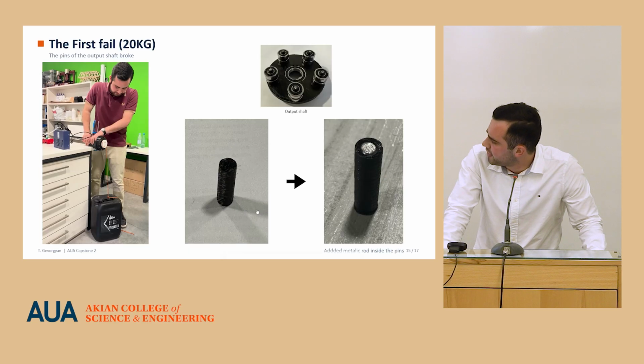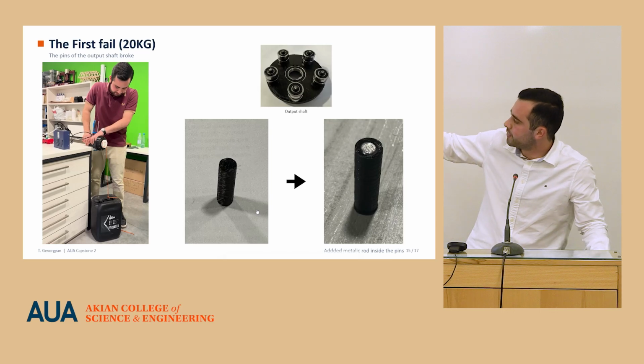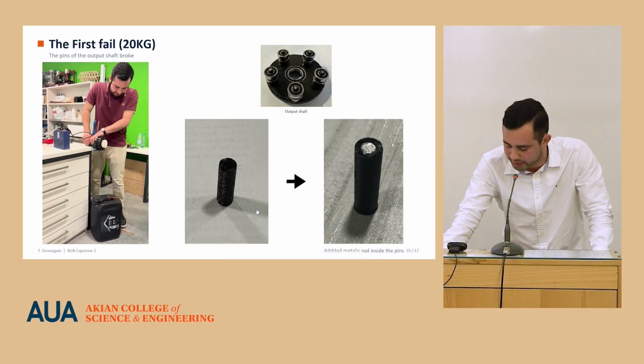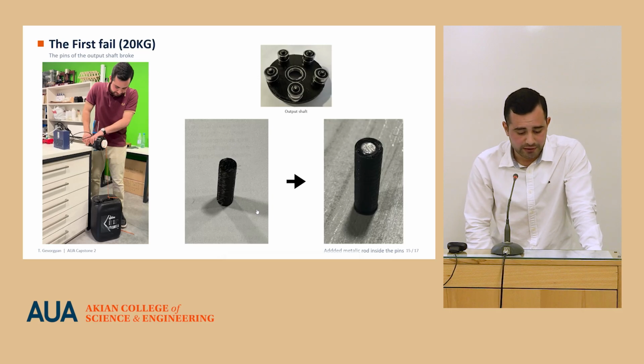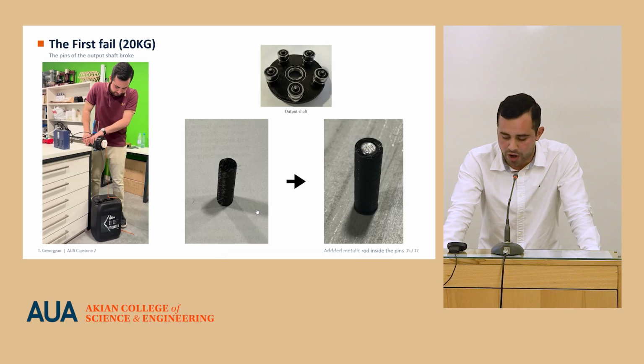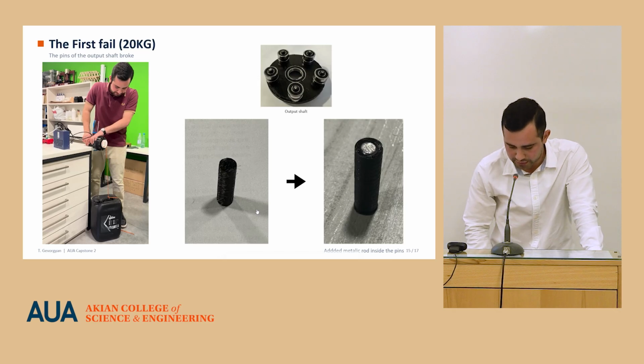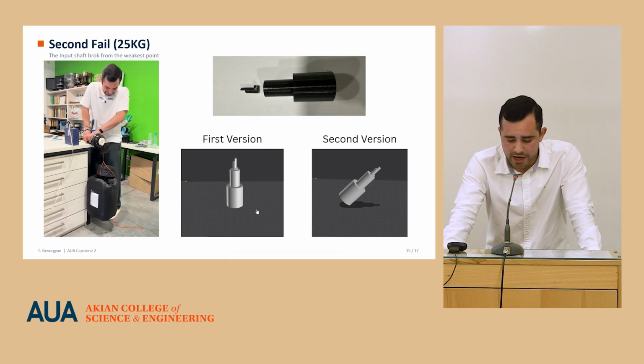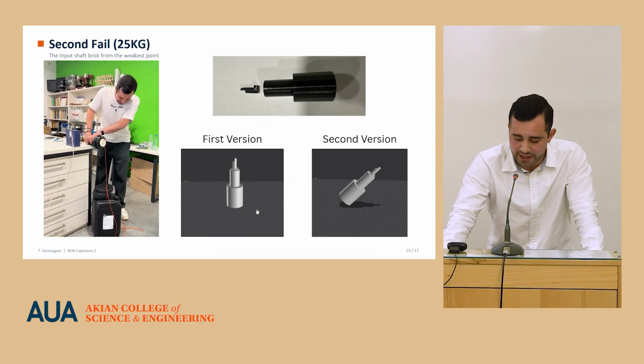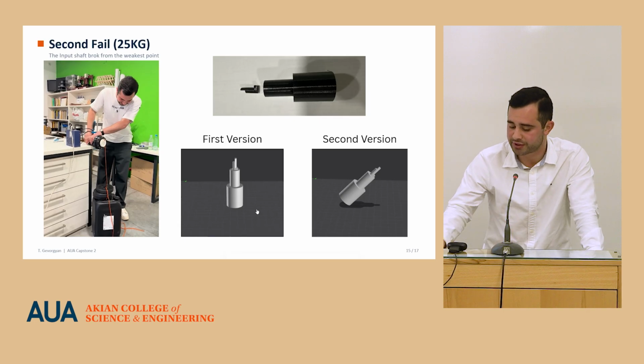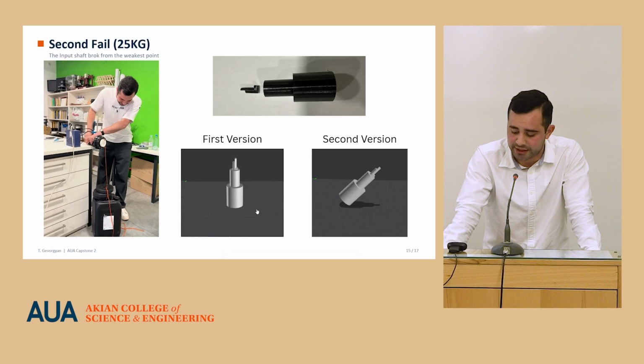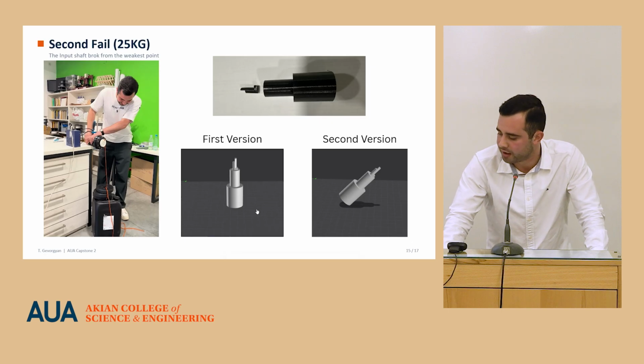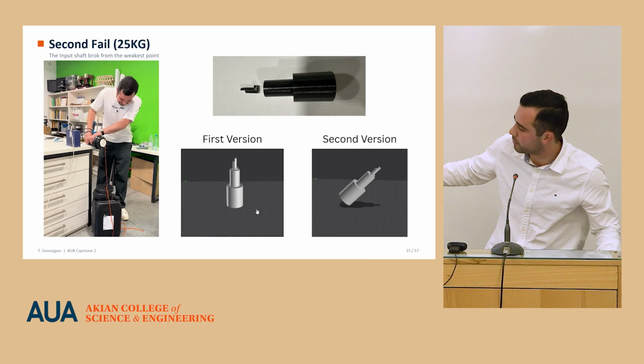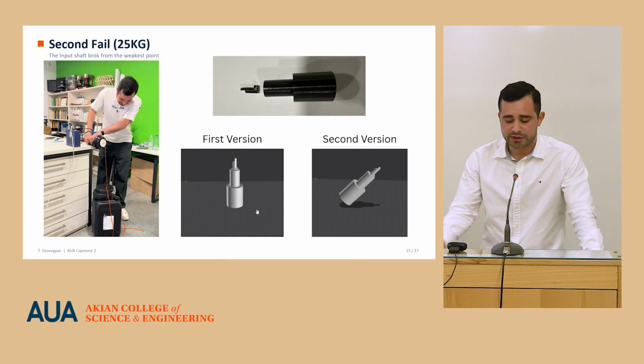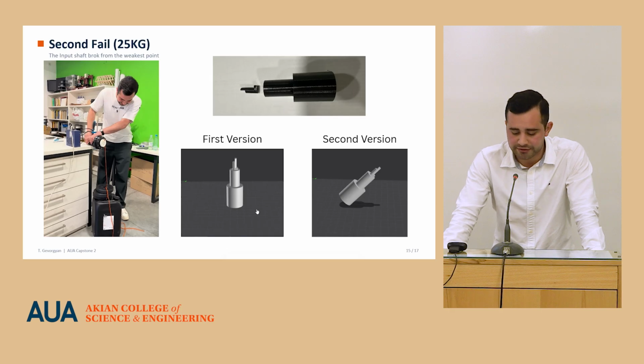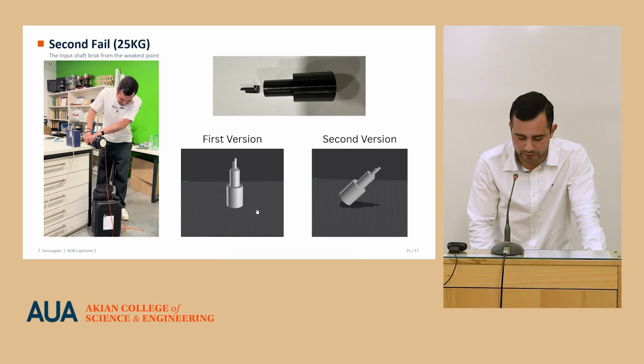And what I did, I redesigned it. I added a hole in it to insert a metallic rod to make it stronger so it would not break. And the second fail occurred at 25 kilograms. After this improvement, I was able to go up to 25 kilograms, and at 25 kilograms another fail occurred. As you can see in the video, the input shaft was broken at the weakest place, and after doing some research, I understood that printing it at a 45-degree angle will make that weakest part stronger because of the layer layout. And after these improvements, I was able to lift 27 kilograms of load.